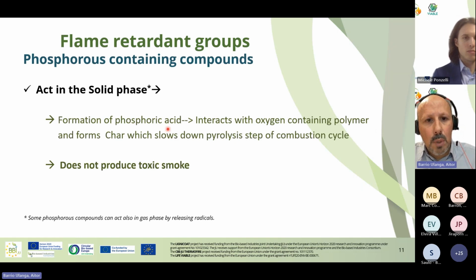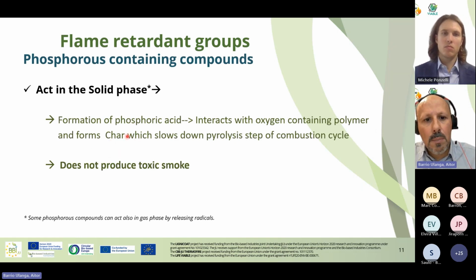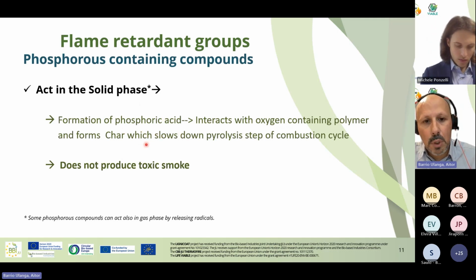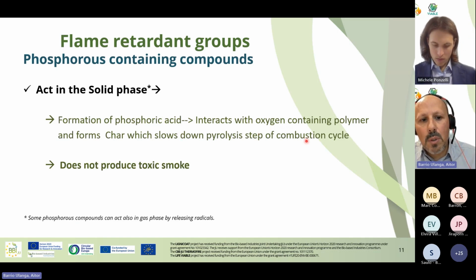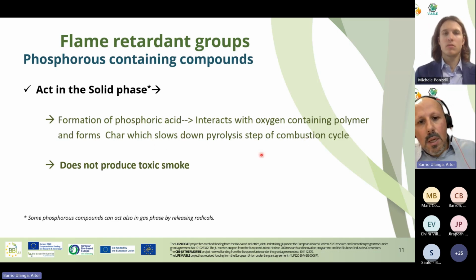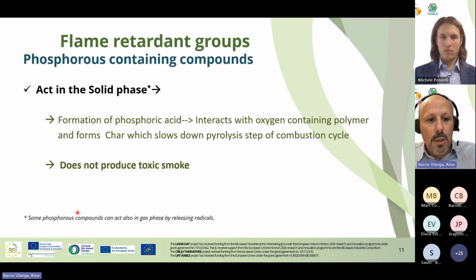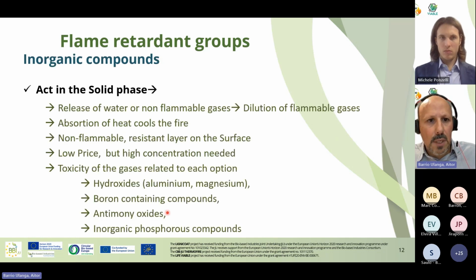Phosphorus-containing compounds are the most used alternative to halogenated compounds at present. And they have two effects. The most known is the promotion of phosphoric acid by decomposition, and the promotion of char in the solid part of the combustion, and it is not toxic. There are some species of phosphorus that also promote radicals that act in the gas phase.